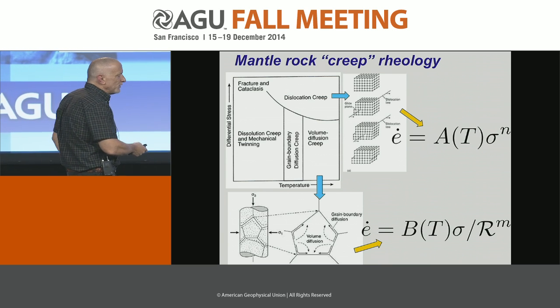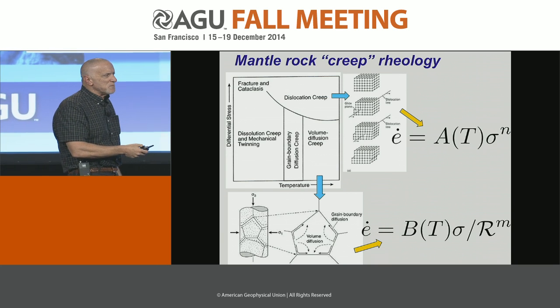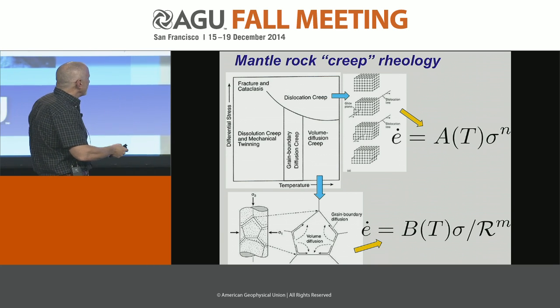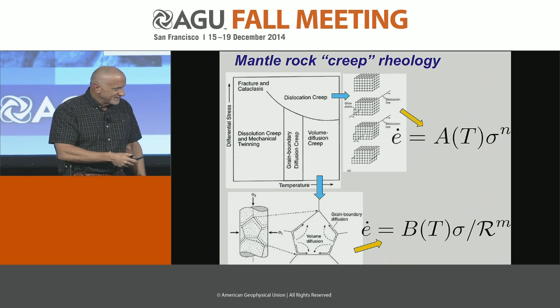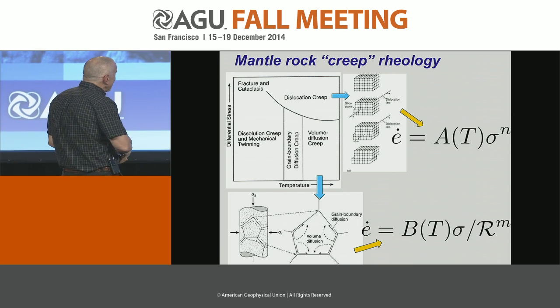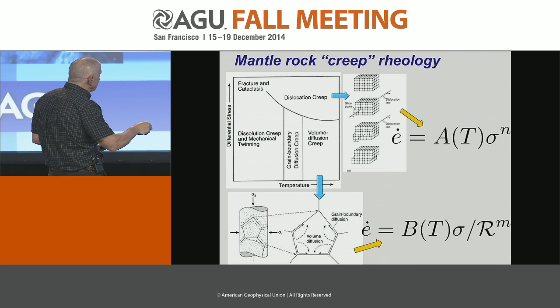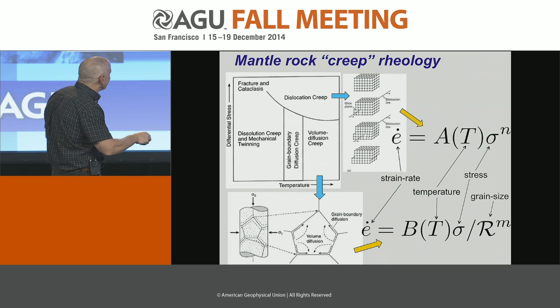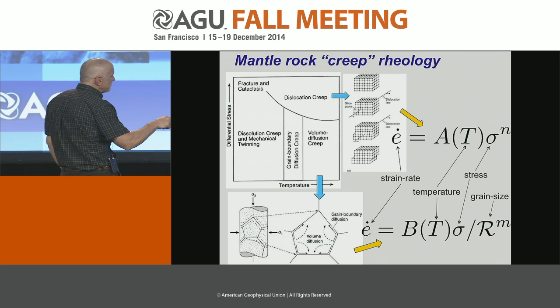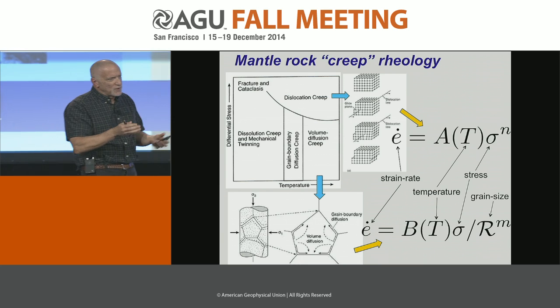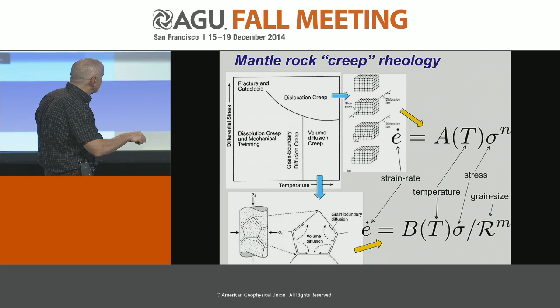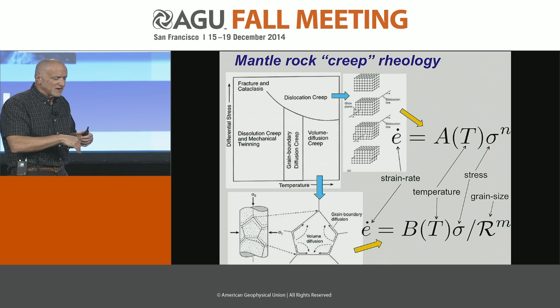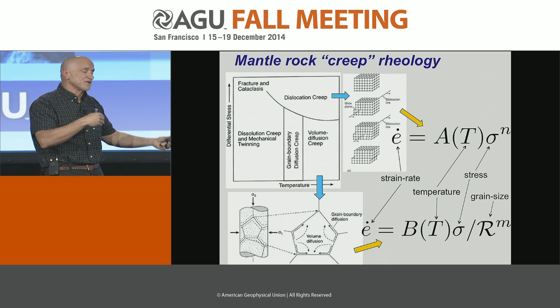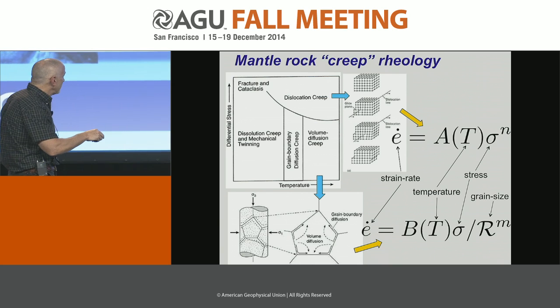So the rheological laws, I try to keep my equations to a minimum here. You may not agree with what that minimum means, but okay. For example, in dislocation creep, we will have a strain rate that is dependent upon a stress to some power. It's called non-Newtonian because it's nonlinear. It's usually a power of 3, and it usually means that as something flows and deforms, it gets weaker and softer. So this is typical of dislocation creep.